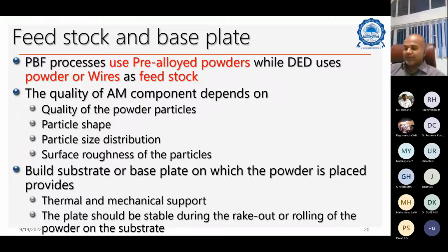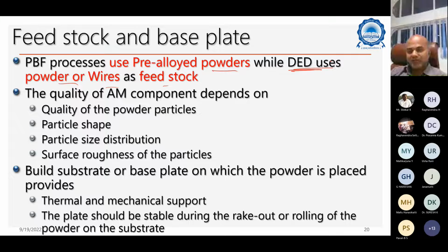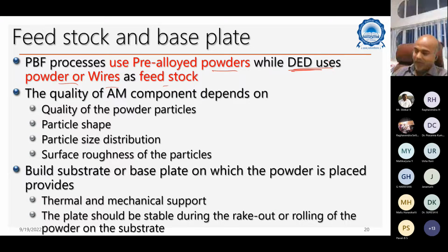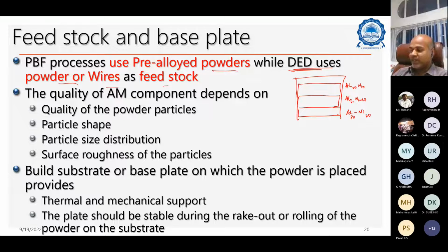Okay. In feedstock and base plate, powder bed fusion generally uses pre-alloyed powders, while DED uses powder, wires, or other feedstock. As I told, one of the key advantages with DED is that you're using powders from different hoppers. So in one layer, let's say you're trying to deposit some aluminum and nickel component. Let's say aluminum 80, nickel 20 in the first layer. Second layer, aluminum 60, nickel 40. Third layer, aluminum 20, nickel 80. You can do this in a DED process.